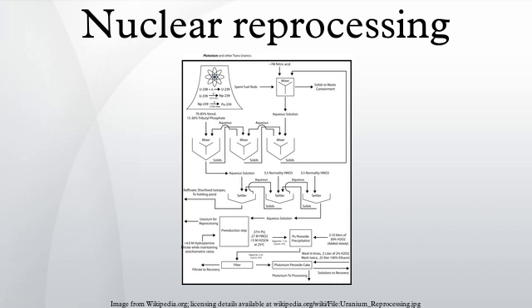Most of the uranium, which makes up the bulk of the fuel, is converted to uranium hexafluoride, the form of uranium used in uranium enrichment, which has a very low boiling point. Technetium, the main long-lived fission product, is also efficiently converted to its volatile hexafluoride. A few other elements also form similarly volatile hexafluorides, pentafluorides, or heptafluorides. The volatile fluorides can be separated from excess fluorine by condensation, then separated from each other by fractional distillation or selective reduction. Uranium hexafluoride and technetium hexafluoride have very similar boiling points and vapor pressures, which makes complete separation more difficult.